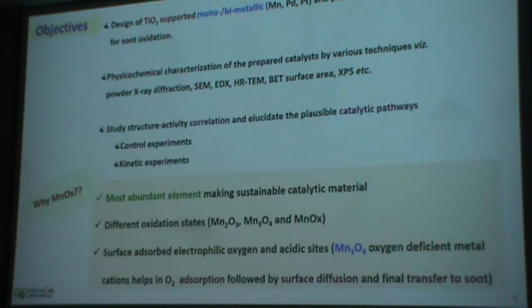Why did I choose MnO? Because it is the most abundant element, making sustainable catalysis, because it is cheap and easily available. It has different oxidation states, 2+, 3+ and 4+, and it can provide surface adsorbed electrophilic oxygen, which is necessary for oxidation reactions, and also Mn3O4 acts as a Lewis acid site, which provides oxygen-deficient metal cations to adsorb oxygen, and it helps in the adsorption and diffusion of oxygen and carrying the oxygen to the soot.